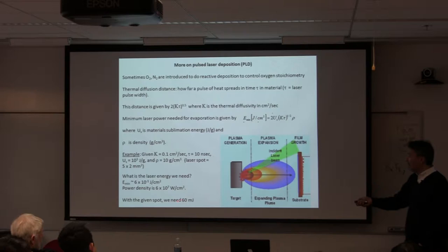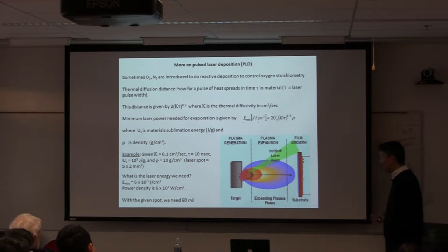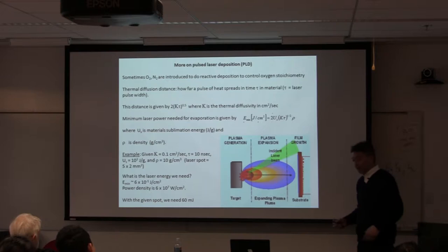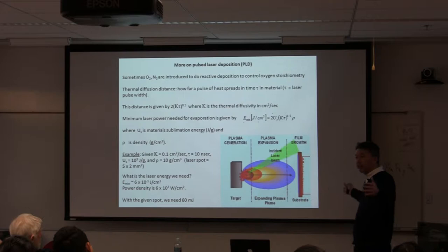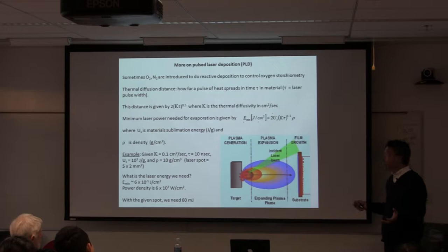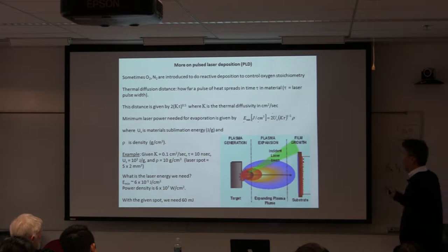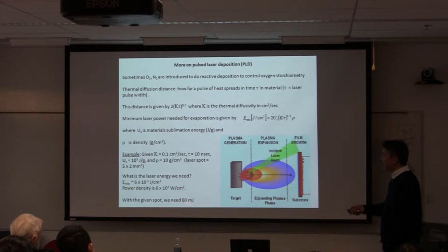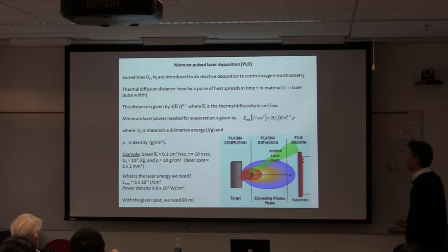There are other laser options since YAG lasers can deliver 60 millijoules. YAG has become a popular laser for PLD. The nice thing about YAG is that it's a tabletop laser at half to a third the price of a big excimer laser. YAG operates at 1.06 μm, so you need frequency quadrupling to reach the right wavelength, which cuts down energy further. But many materials can be deposited with as little as 15 millijoules, and YAG requires less maintenance — you can plug it into the wall.